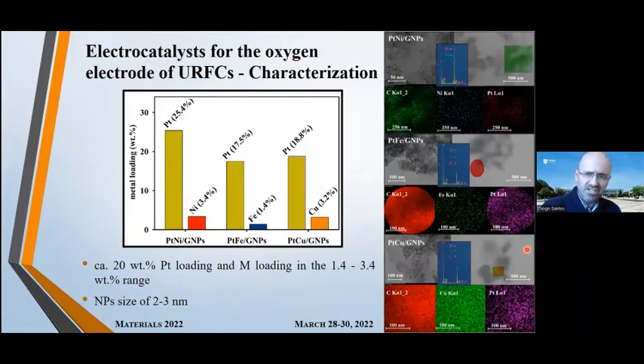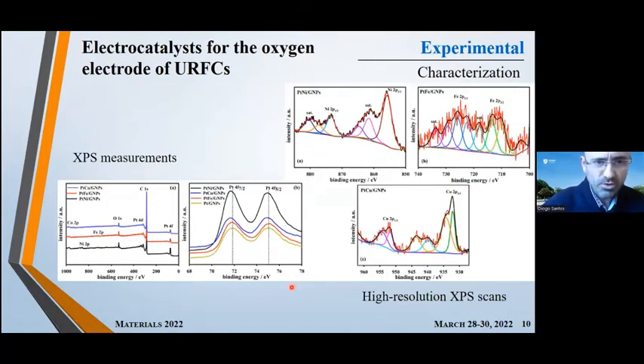Then we have done the characterization of these materials. They all have about 20% platinum, and the amount of the transition metal ranges between 1.4 for iron up to 3.4 in nickel. This was measured by ICP, and we have done also TEM analysis along with the elemental mapping and the EDX spectra, and we've seen that the nanoparticle size ranges between 2 and 3 nanometers. We have also done XPS measurements of the catalysts, and here we also show the high resolution XPS scans that confirm that the materials had the composition that we expected.